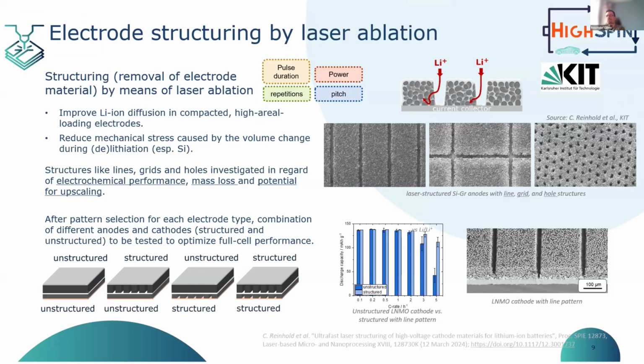There are different parameters that we can work with here, and some of them are given here. For example, we can vary the pulse duration of the laser, the number of repetitions or passes over the electrode to ablate the material, the power of the laser, and also the pitch distance between the grooves and etchings that are made with the laser. We can consider different patterns that can be etched or ablated on the electrode. You can see, for example, line patterns, grid patterns, or hole patterns.